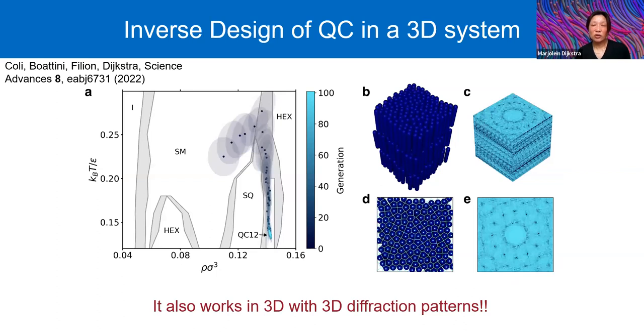And then finally, we also extended it to a three-dimensional system, rod-like particles that also interact with a soft core shoulder. And in this case, it was also able to find this 12-fold quasicrystal. In this case, we had to use three-dimensional diffraction patterns, which are very complicated to classify by human eye, but a neural network really doesn't care whether the dimension is bumped from 2D to 3D, so it was able to recognize these 3D diffraction patterns.